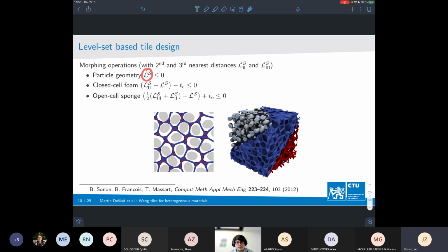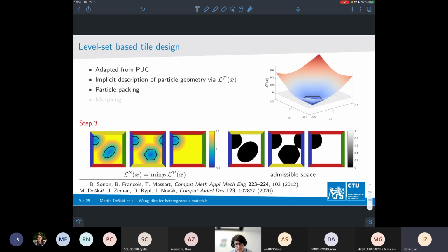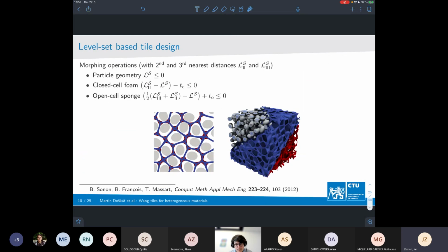If, with the signed distance function, we also add some function which gives us the same information, which is the distance to the second and third nearest interface, then using linear combinations of these individual functions, we can, using exactly the same type of information, generate this open cell type of microstructure just by evaluating this simple condition. And using this third one, again, by checking this simple condition, we can generate a microstructure like here. But again, all that is based on the same input data, which is this level set type of representation concerning the first interface and possibly second and third. But this is all possible, and in the Wang tile setting, it just requires some additional bookkeeping.